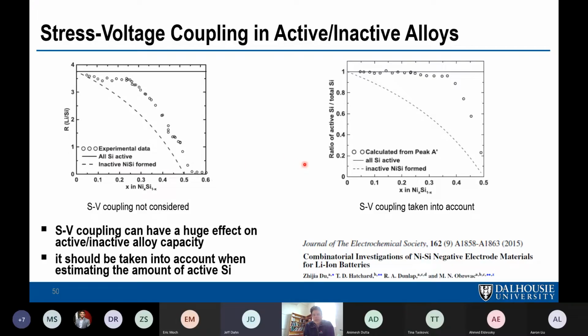But if you actually calculate how much silicon is there from that upper potential plateau, you find out all the silicon is actually active. And nickel is one of the few transition metals, it turns out, where the silicide is actually completely active. The two are copper and nickel, the most noble transition metals. The more electropositive transition metal silicides are all completely inactive. Nickel silicide is active if it's nano enough, because the kinetics are not great. But if you make nickel silicide nano or amorphous, all the silicon is active in it, but you don't see all the capacity from silicon because its potential is shifted to negative potentials.